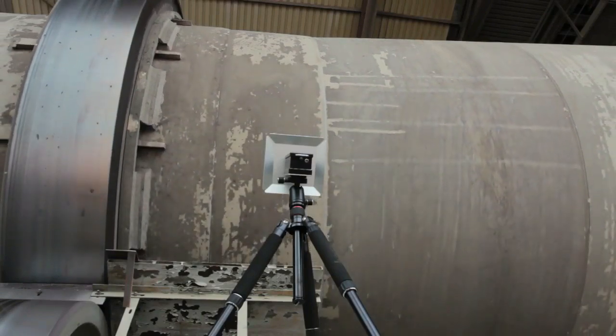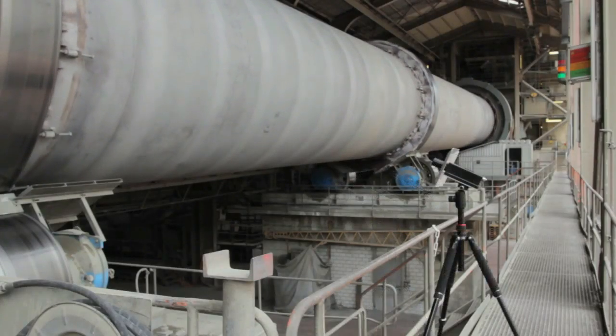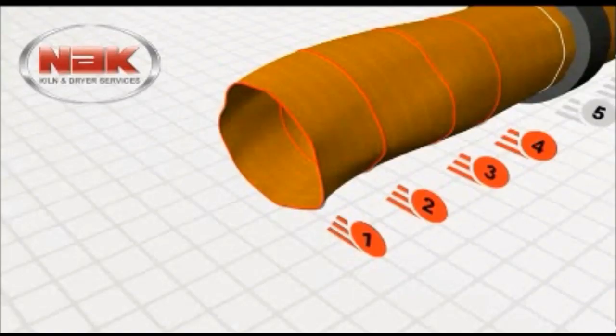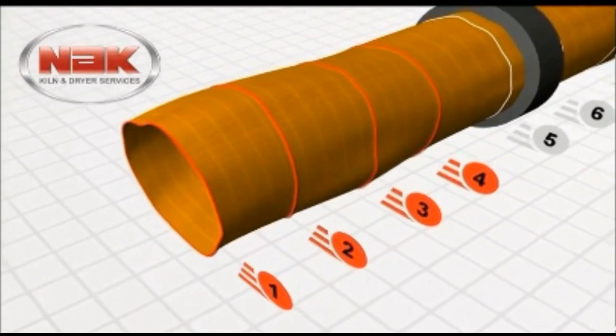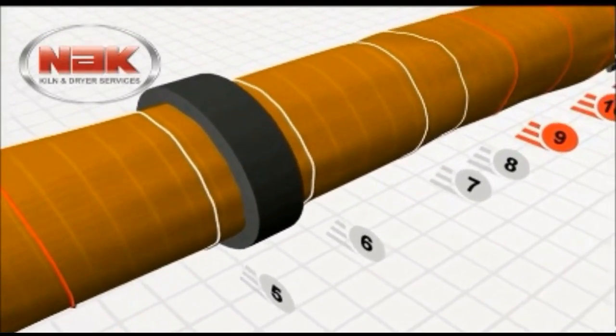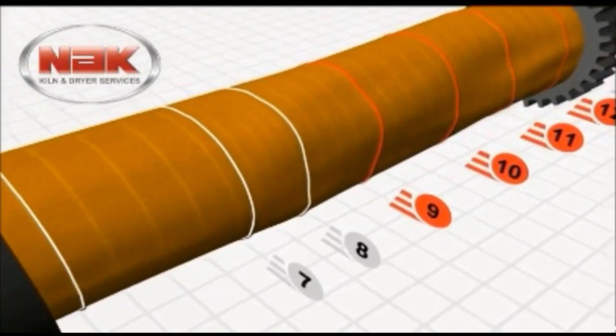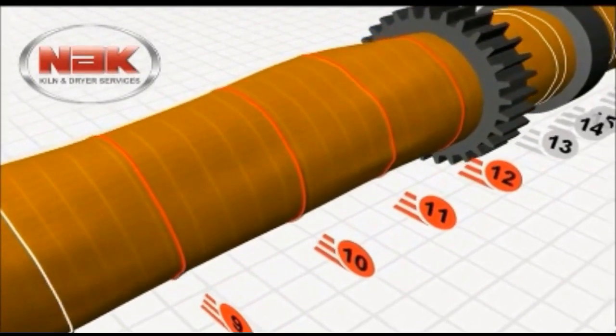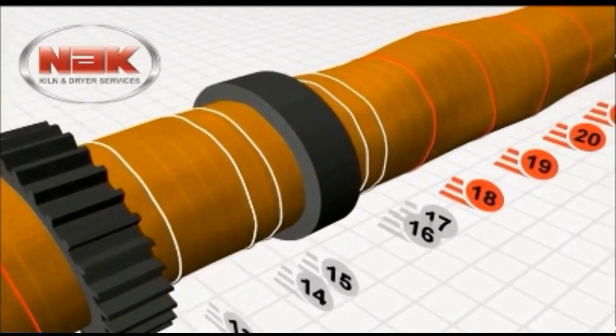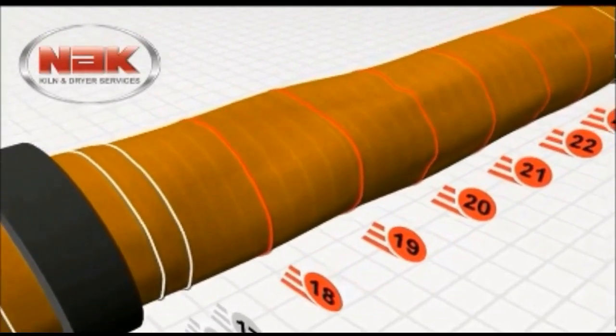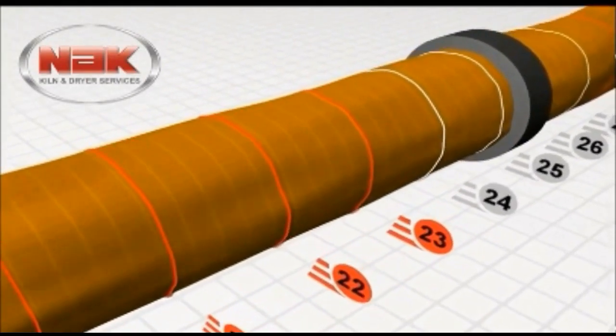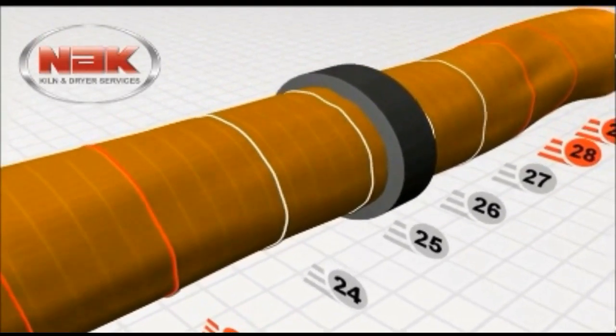The more cross sections are measured, the more detailed the picture of the kiln. Areas to focus on include: areas of refractory failures to check if roundness deviation in the shell is the root cause; areas of kiln inlet and outlet to know the impact on seals; areas of kiln tires to see the impact of shell deformations on tire wobbling; areas where shell sections need to be replaced to find good locations with low run-out where new shell pieces can be easily connected; and areas of the girth gear in case of gear replacement if the shell needs to be replaced as well.